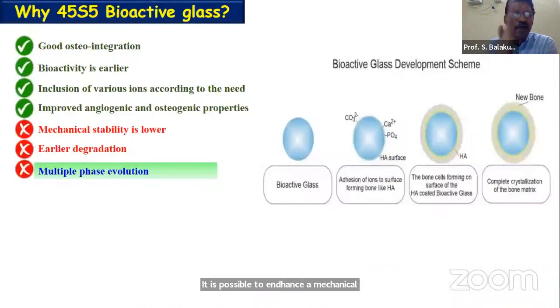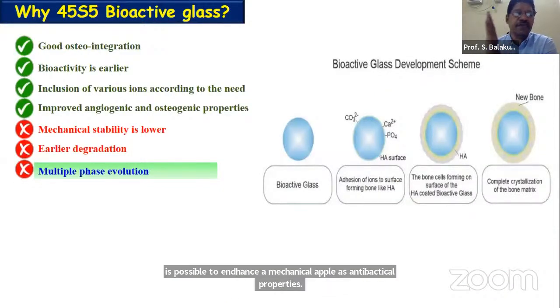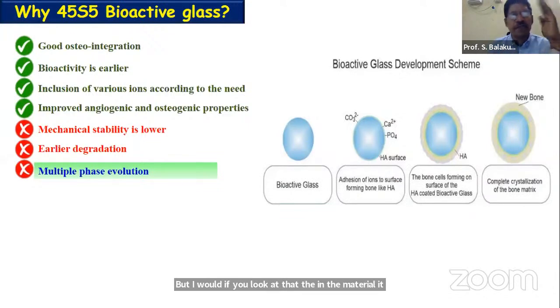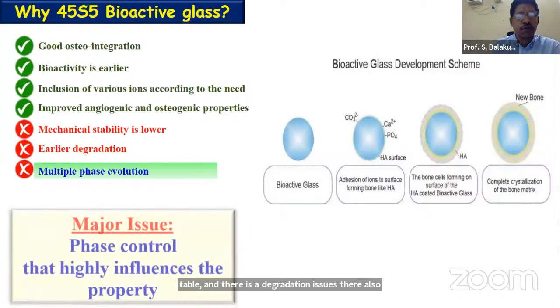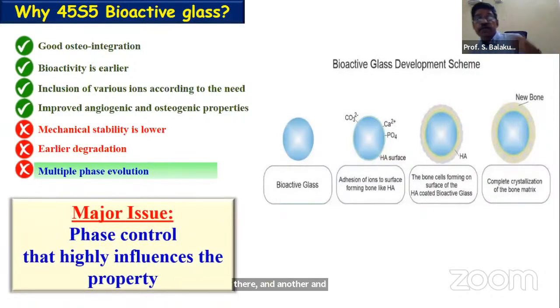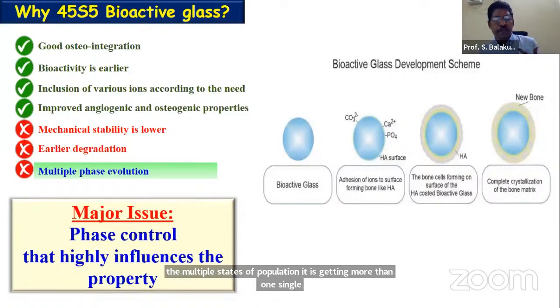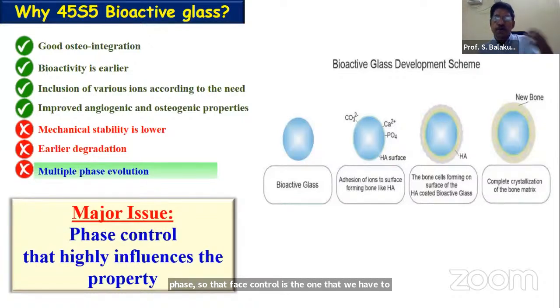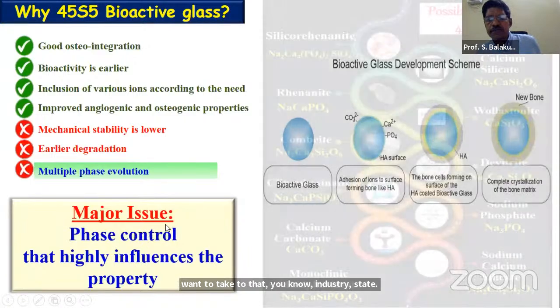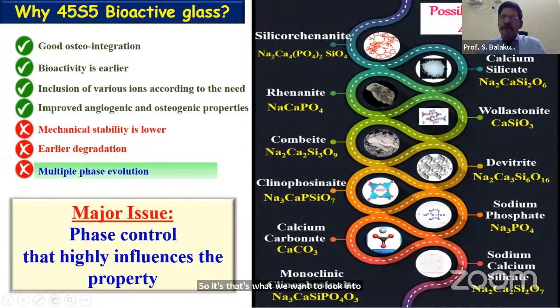But if you look at the challenges in the material, it is about making the material stable, and there are degradation issues there also. Another issue is multiple phase formation. It is getting more than one single phase. So phase control is what we have to focus on when you want to make this material and take it to industry scale. That is what we want to present here. We have systematically evaluated what we have done with the different process conditions and different methods.